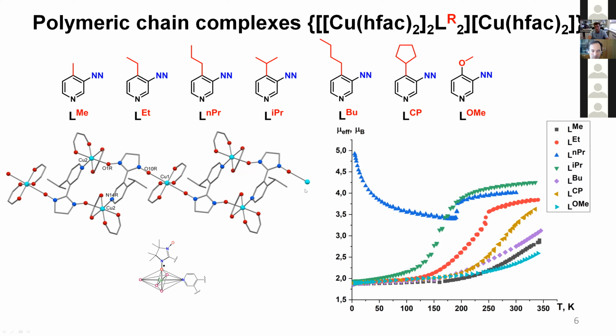For example, in the complex with ethyl substituted nitronyl nitroxide, the copper-oxygen distances are equal at 250 Kelvin to 2.2 angstrom, and upon cooling to lower temperatures in one of the dimers, the distance remains almost unchanged, while in the other it is reduced. Then with cooling, the distances continue to gradually decrease, and at low temperature become almost equal, about 2 angstrom. In the chain with propyl substituted nitronyl nitroxide, it is the blue line here.